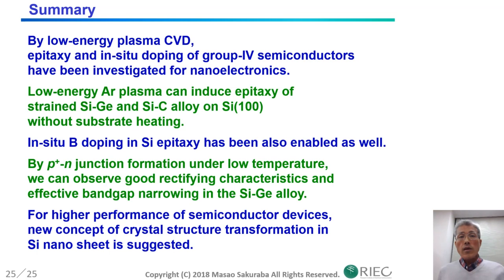By P plus N junction formation under low temperature, we can observe good rectifying characteristics and effective bandgap narrowing in the silicon-germanium alloy. For higher performance of semiconductor devices, a new concept of crystal structure transformation in silicon nanosheet is suggested. Thank you for your kind attention.